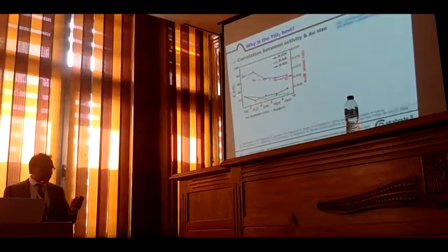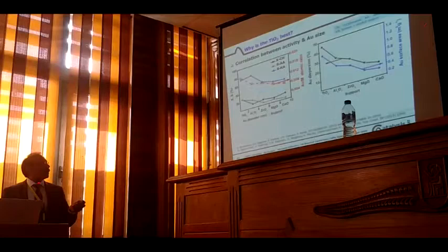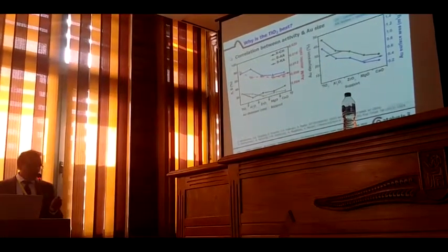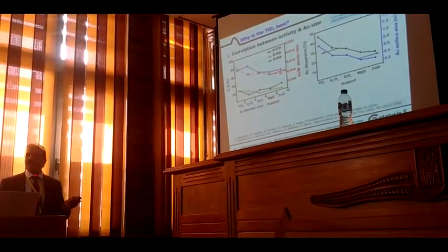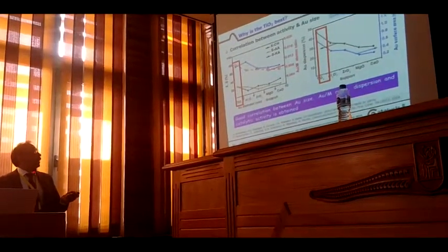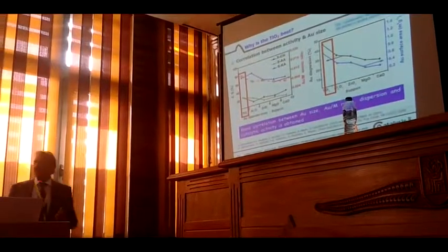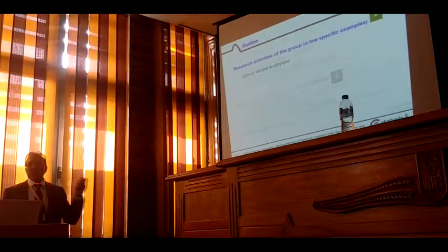And then we also calculated the dispersion and the active metal area of gold. It's not the total BET area, it's the active metal area of gold. These are also high in the case of titanium. So it is quite convincing that a good correlation between particle size, gold enrichment, dispersion, and catalytic activity is obtained. Hope you are convinced with this. And now I finish the